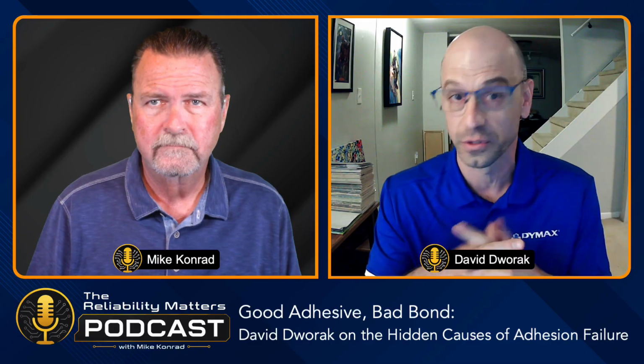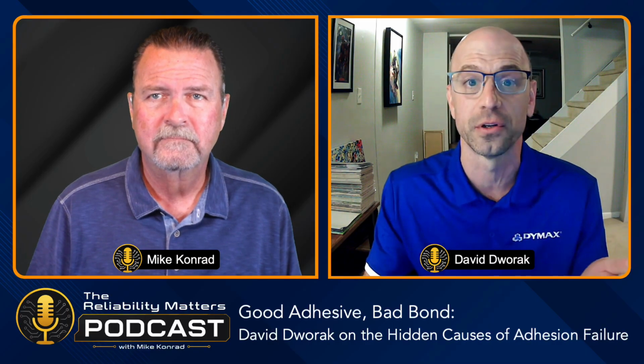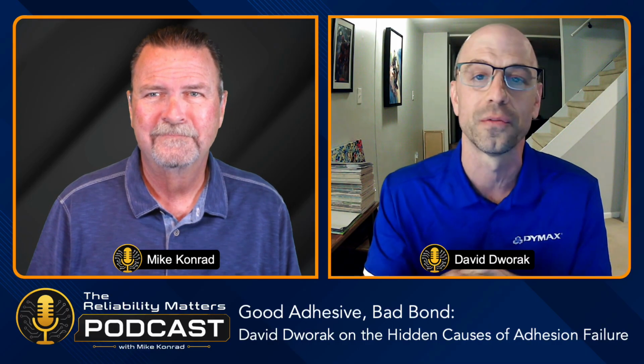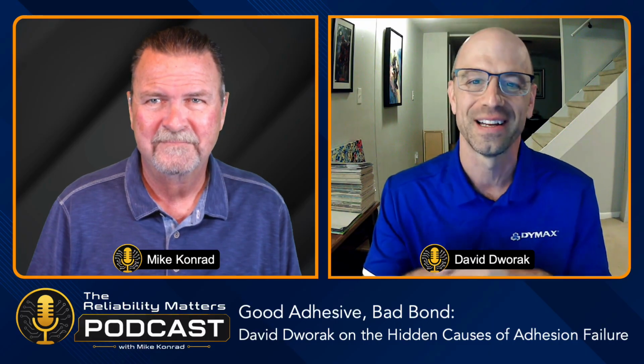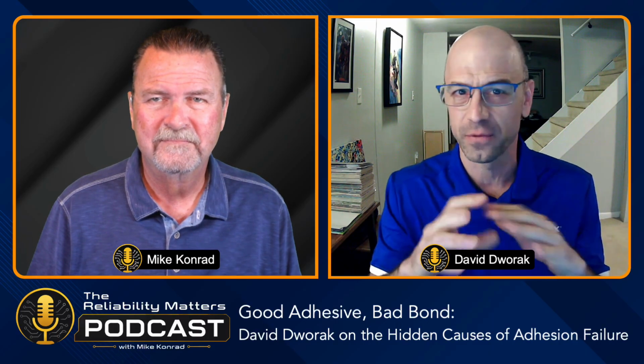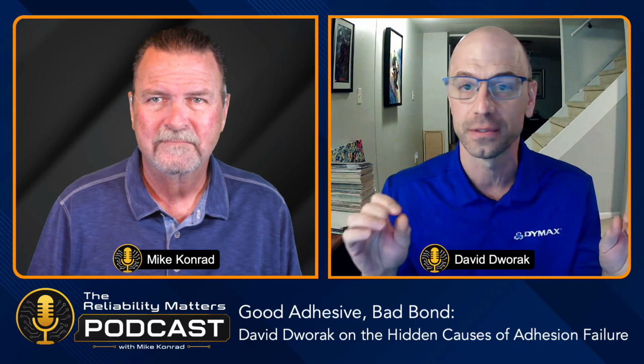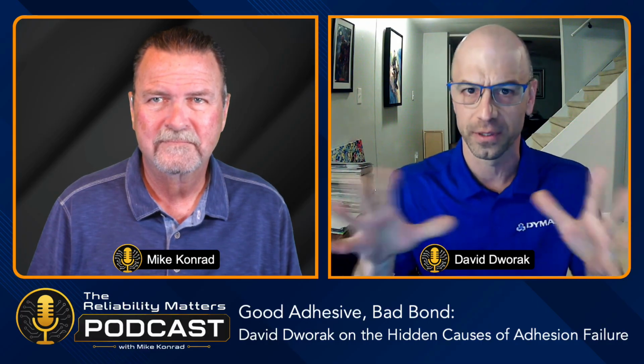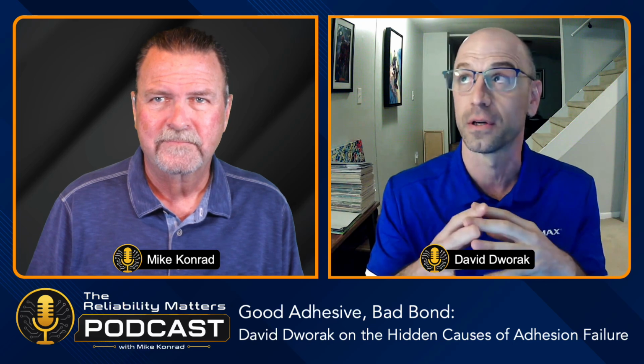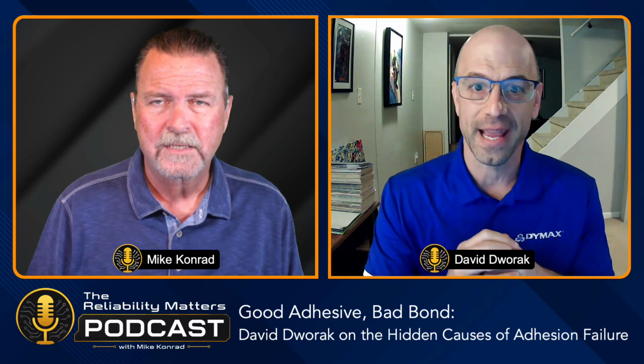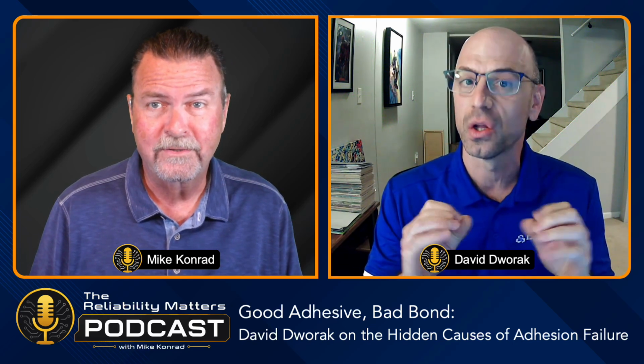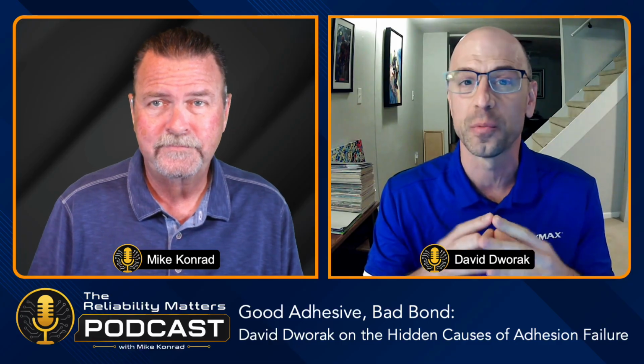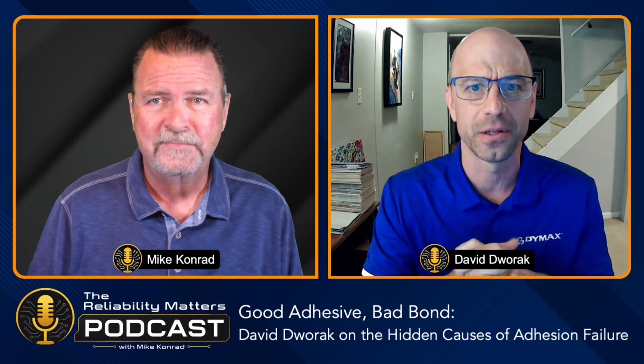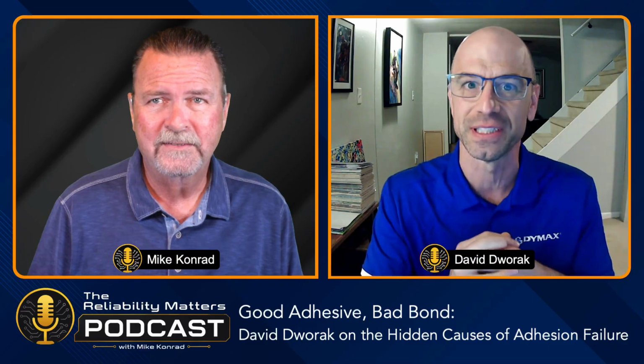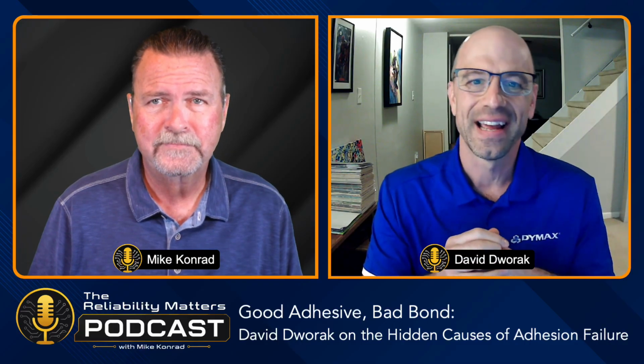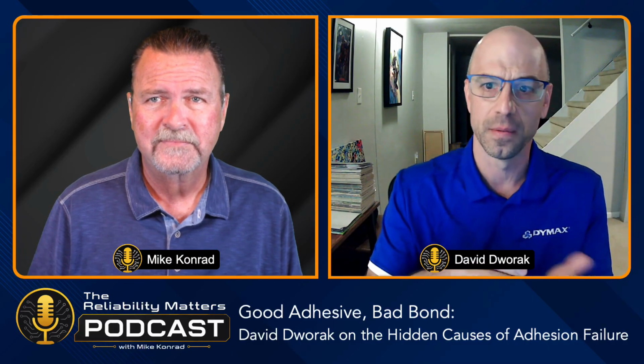Everyone's familiar with Teflon, so well known for being a very difficult to bond substrate. If you look at the surface, everything is stable. There's no push or pull, the carbon and fluorine is good. And so Teflon would be a very low surface energy material. Exactly. Very similar to polypropylene. Not much for those water molecules or adhesive to interact with because the surface is so stable. You put a drop of water on and it will bead up.